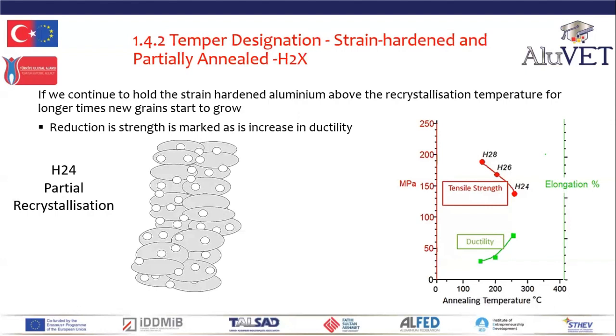Thus, through controlling the degree of recrystallization in strain hardened structures, we can control or adjust the strength and ductility. The strain hardened cold work structure is said to be partially recrystallized. The H24 half hard temper is a balance between strength and ductility.